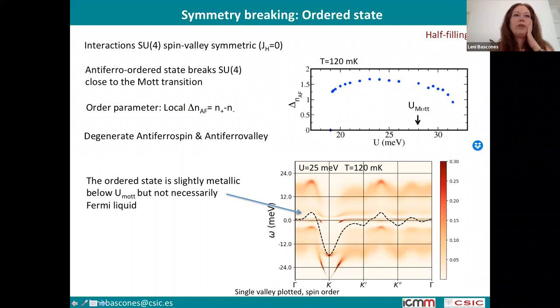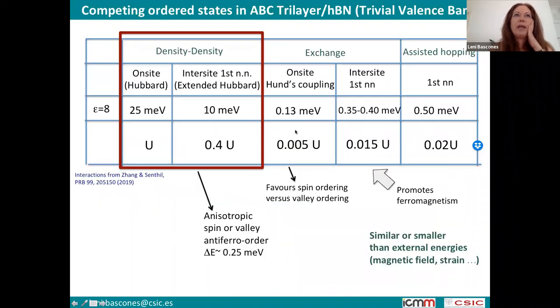Now, the question of whether we expect this state. So before, I said okay, these terms are much larger than these other terms, which is true. But now here, if we look at these terms, we can see that Hund's coupling is there. This will select one of the orderings that we have found, this antiferromagnetic ordering with respect to the valley ordering.